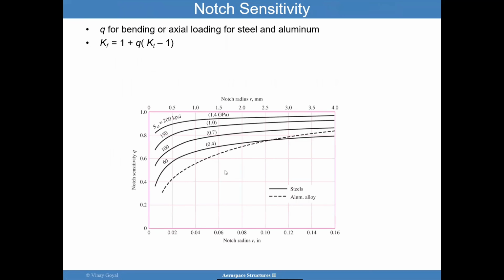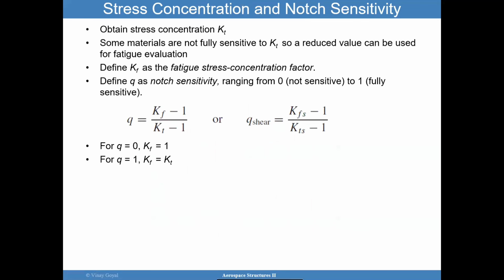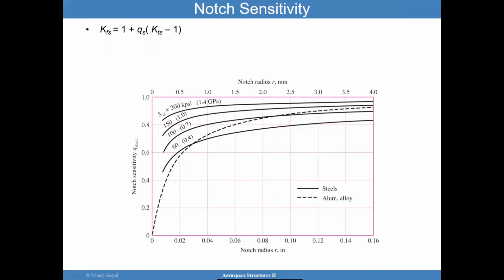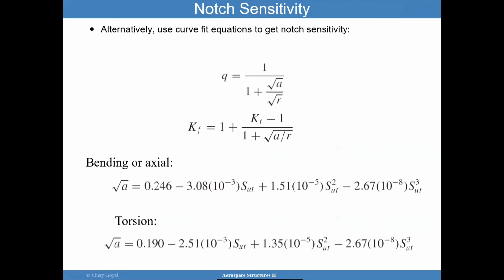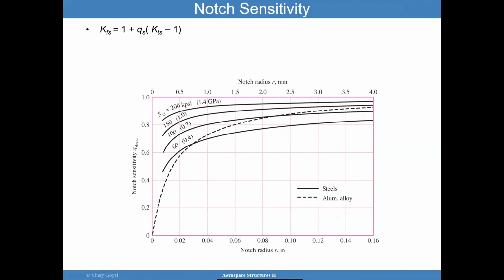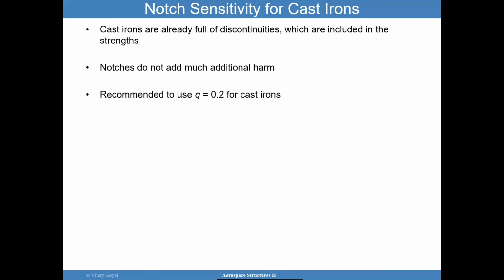You can see here a notch radius is going to have different notch sensitivities. The bigger the notch radius, the notch sensitivity is less. So if q approaches 1, then Kf becomes Kt. But for very small notch radius, you start getting a q closer to 0, which means that Kf becomes 1. And I'll explain what Kf is, basically your fatigue stress concentration factor. For shear, you also have a very similar formula. These are the equations if you didn't want to use the curves, but we'll skip that. And for most cast irons, q equals 0.2 is a good value.